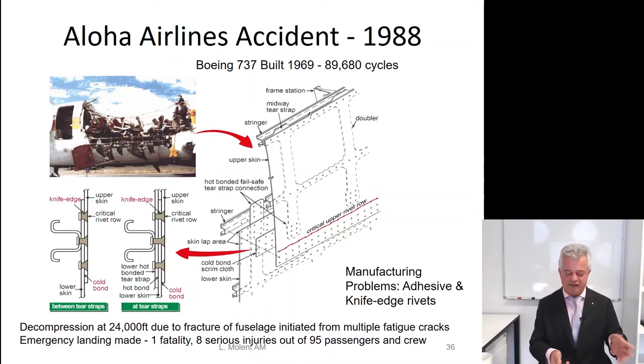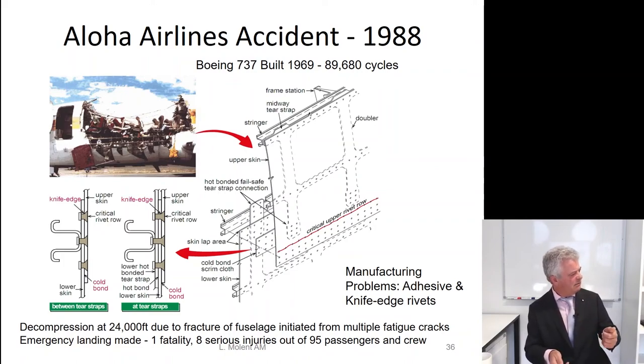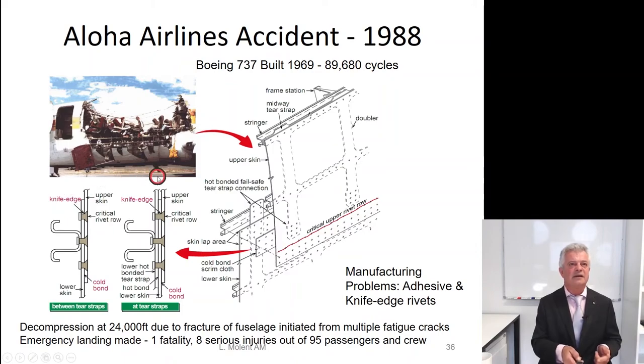The adhesive gave up the ghost in this Hawaiian tropical environment, leading to fatigue from the fasteners. The fatigue nucleated because the fastener heads were countersunk to produce a very sharp knife edge. And these are the highly loaded areas of the fuselage. A manufacturing defect coupled with high stresses killed a few people, and caused the aviation industry to go into virtual meltdown, because this was kind of a new phenomenon. We won't dwell on it. High stresses and a manufacturing defect.